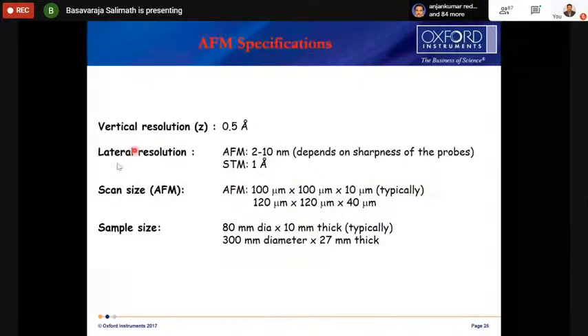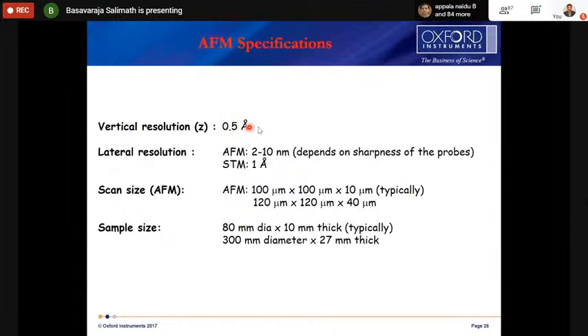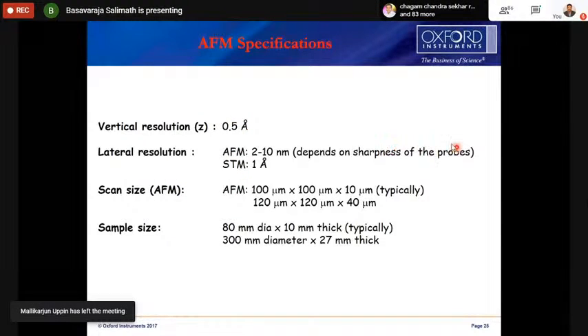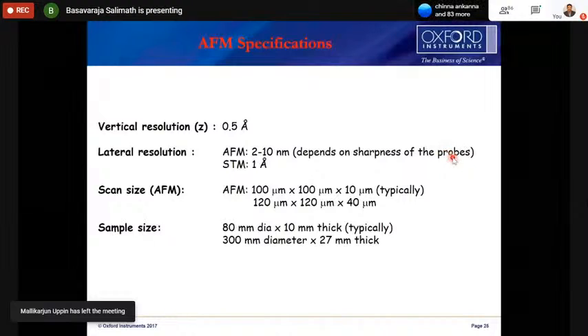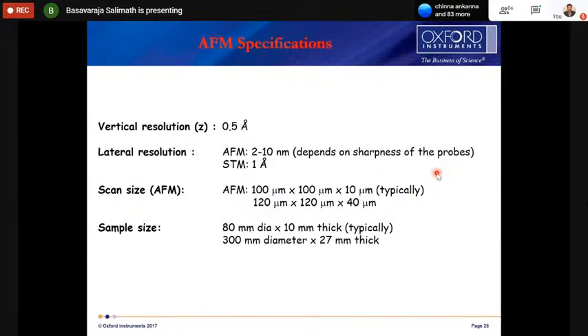So now coming to the AFM specifications, the vertical resolution can go up to 0.5 angstroms, and the lateral resolution depends on the sharpness of your probe. If your tip size is 2 nanometers, then we can get 2 nanometer resolution. In the case of STM, actually it's 1 angstrom lateral resolution.